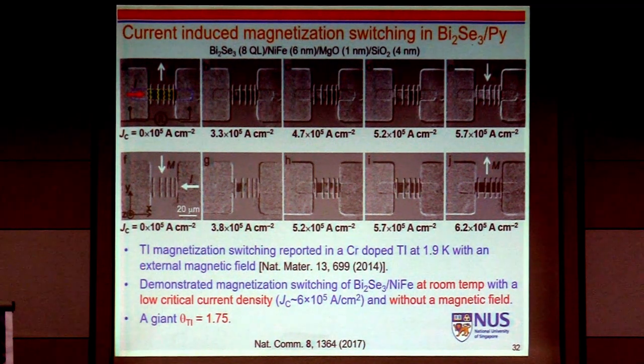Then we apply charge current from the left electrode. Initially, the black domain indicates everything is saturated in this direction. As we increase the charge current, you can see the white domain is getting larger and larger. And eventually, we can switch everything to the opposite direction. From here, we can inject charge current from the right electrode. We can see the black domain propagate, and everything is now saturated to the initial direction. This is measured at room temperature, and the current density was 6 times 10^5 ampere per square centimeter. So it's like 2 orders smaller than the heavy metal case, without any magnetic field, because we are dealing with an in-plane magnet. And the extracted spin Hall angle was